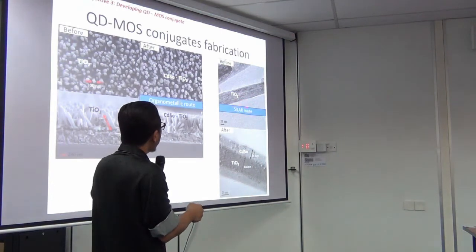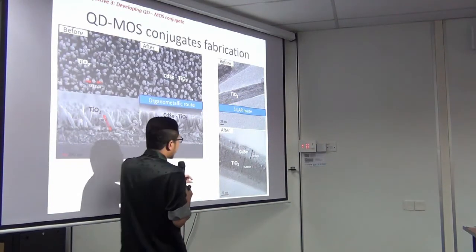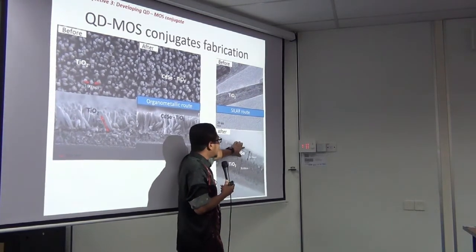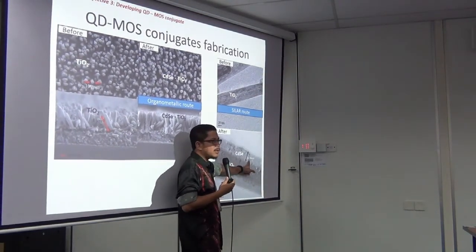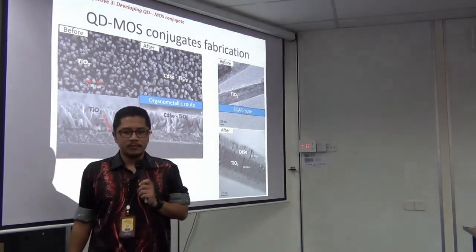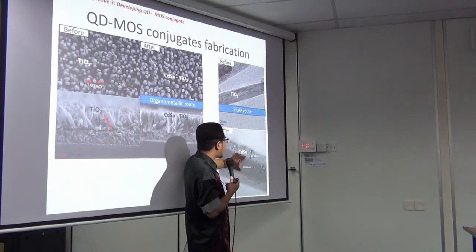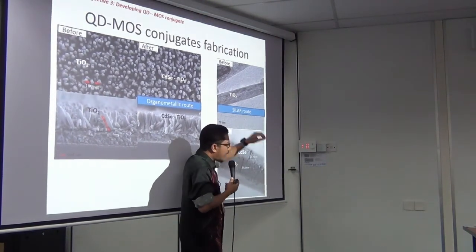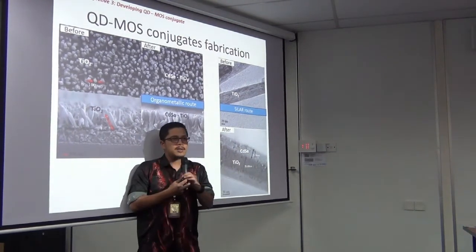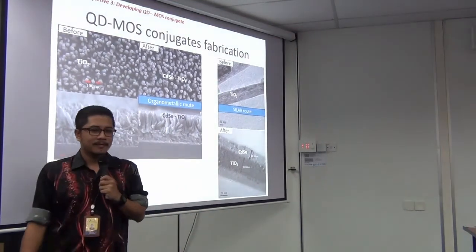So this is before, we have nanorods of TiO2, and this is after. It's quite thick. The diameter of the TiO2 nanorod is 35.68 nanometer. After the SILAR procedure, the thickness of CdSe is 21.36 nanometer. Is this a quantum dot? Can we consider this one as a quantum dot? No?